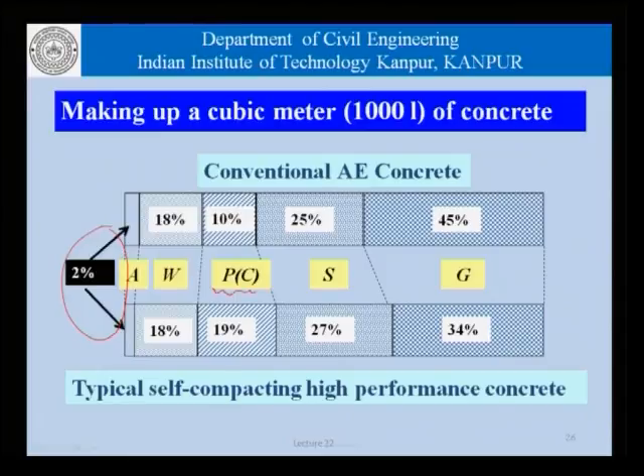As far as powder or cement or fines is concerned, there is a marked difference. That is about 10% in conventional concrete, whereas in self compacting concrete it could be as high as about 18 to 20%. The sand is not really so much different, and this increase here is compensated by a corresponding decrease in the coarse aggregate percentage. So, in the end result, self compacting concretes have a larger paste volume compared to conventional volumes, and this is compensated or made up by the reduced volume of coarse aggregates,